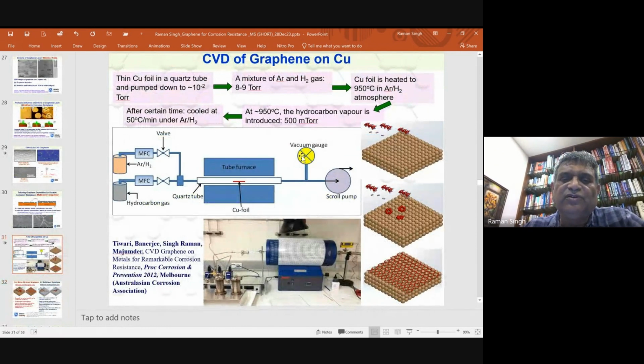So we started to develop our own graphene. I will quickly go through how we develop graphene by chemical vapor deposition. You take the metal on which you want to develop graphene, that is copper or nickel. And why copper and nickel? I will talk about that in a sec. So you take copper, place the copper inside the furnace, you pass hydrogen and you heat it to 900 to 1000 degrees Celsius. And why are you passing hydrogen? Because every metal has a native oxide, a layer of copper oxide. In this case, copper oxide will react with hydrogen and water will be pumped out and pristine copper will be left behind. And you need pristine copper because copper and nickel are very good catalysts for splitting hydrocarbon. So when you supply hydrocarbon in a very controlled way using this mass flow controller, that hydrocarbon will be split into carbon and hydrogen.